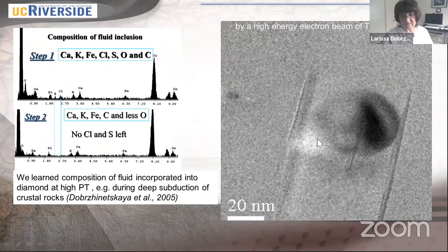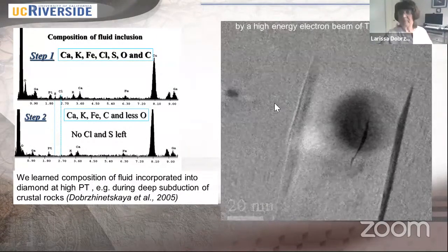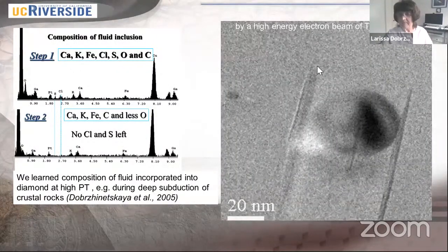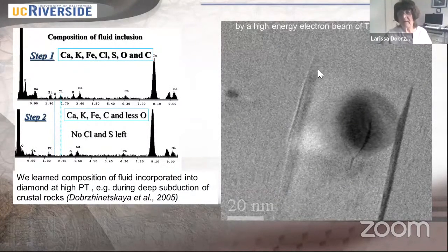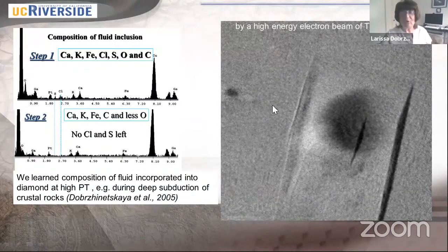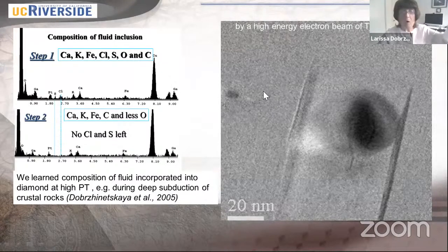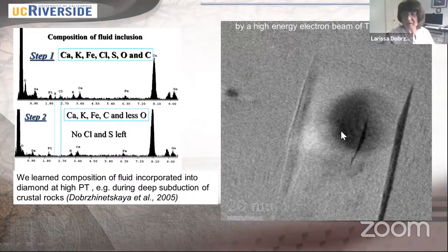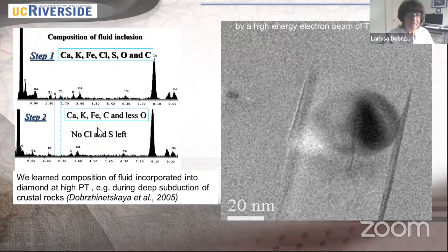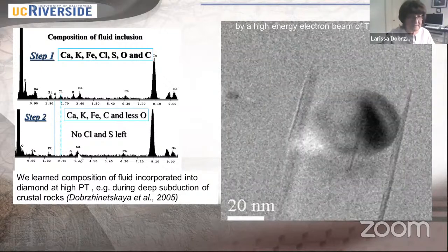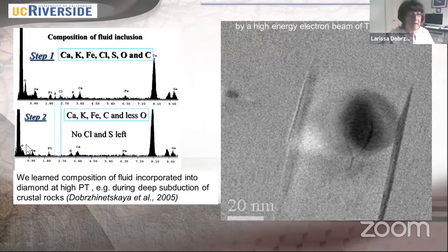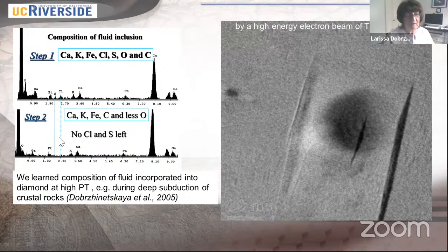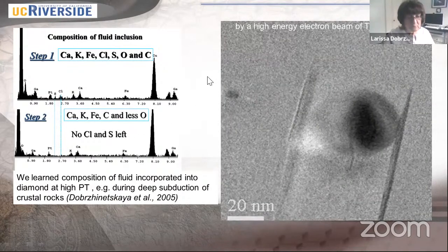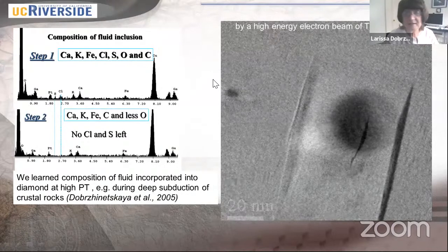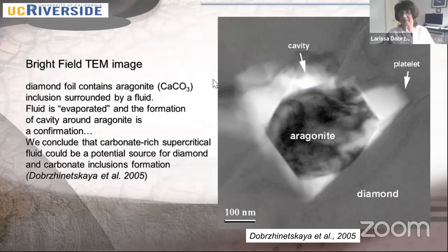But when the fluid was evaporated, we know this happened in a vacuum chamber. Part of the material precipitated around, but we don't have the volatile materials because they're gone. So really, when we measured material around, we found that there is calcium, there is potassium, okay, you see these peaks, still there is iron, but less oxygen. We don't see any chlorine and any sulfur left. So we understand now the fluid composition.